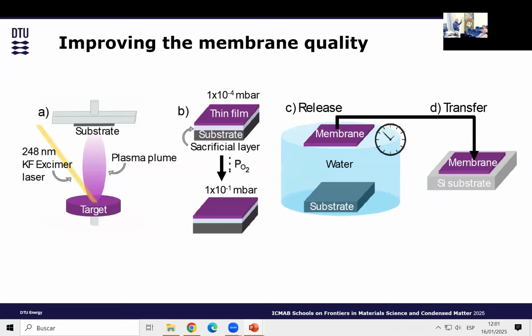We wanted to reduce the material because the hypothesis was that if we create oxygen vacancies at the superficial layer, it will dissolve faster. That was the hypothesis. And then we grew the films at a different partial pressure. We put it in the water. We measure the time that it dissolves, and then we look at the membrane and we characterize the membrane. How good are the membranes?